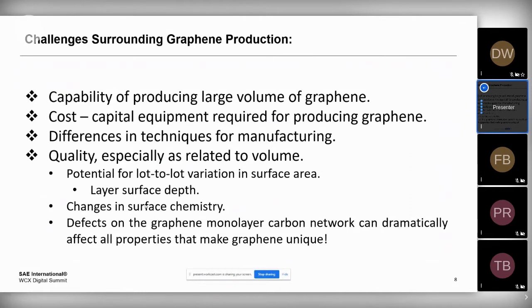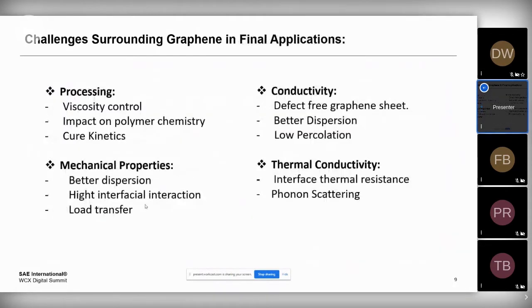But another challenge that comes out of this is if you have differences in technique, you have issues with respect to how you control quality. And there's potential for lot variation in surface area, layer surface depth, changes in surface chemistry, and defects that can dramatically change or affect all the properties that make graphene unique. With respect to final applications, there are also other challenges, including processing and viscosity control. What does it do to your cure kinetics? Does it change your polymer chemistry? Does it affect your ability to achieve conductivity? Are you able to get a defect-free graphene sheet? Are you able to achieve improved dispersion or low percolation?